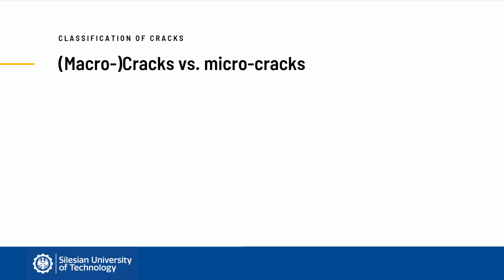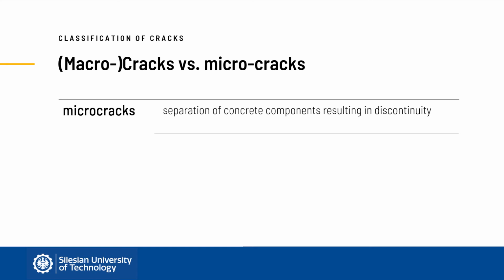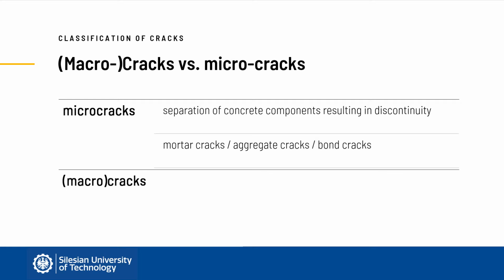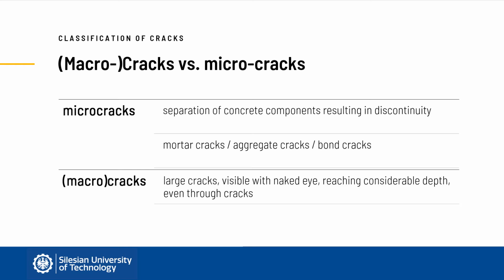Whatever the source of cracking, cracks can be further classified into macro and micro cracks. Micro cracks are small, pore-sized discontinuities in concrete components. They can be formed within the mortar or less frequently in the aggregates. The delamination between the aggregate and mortar is also not uncommon. They usually have random character and are spread over a larger area or through the volume of the element. Macro cracks, in turn, are what we usually call cracks. These are large cracks of considerable height and depth. The most important characteristic which distinguishes micro and macro cracks is the involvement of reinforcement in case of the latter ones.